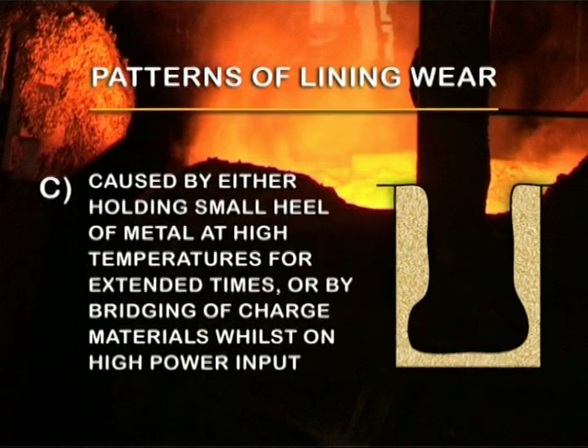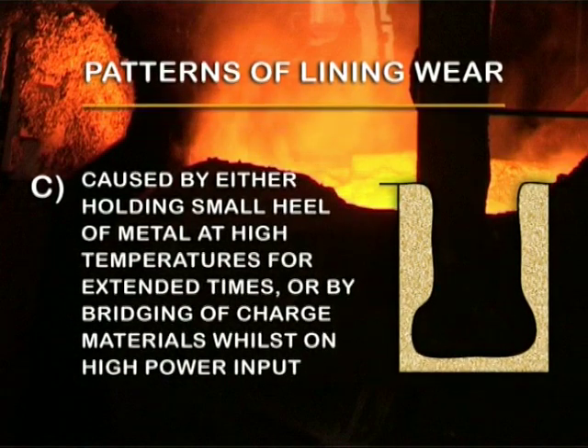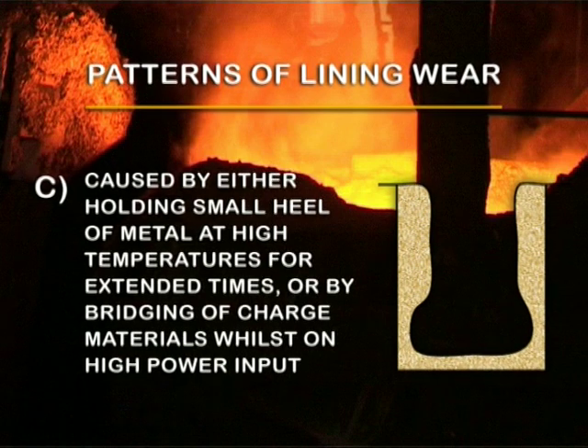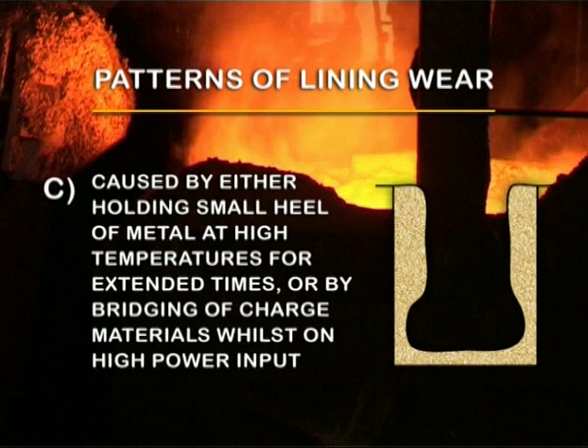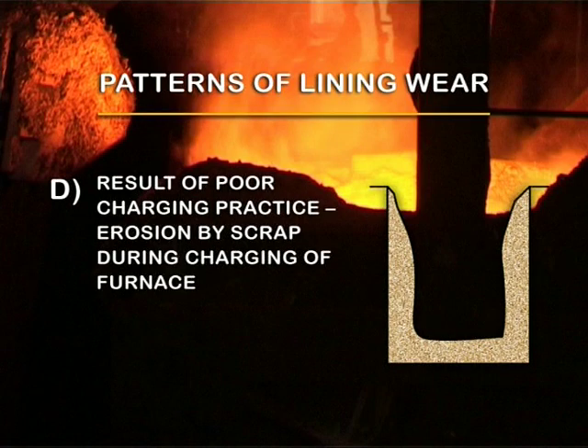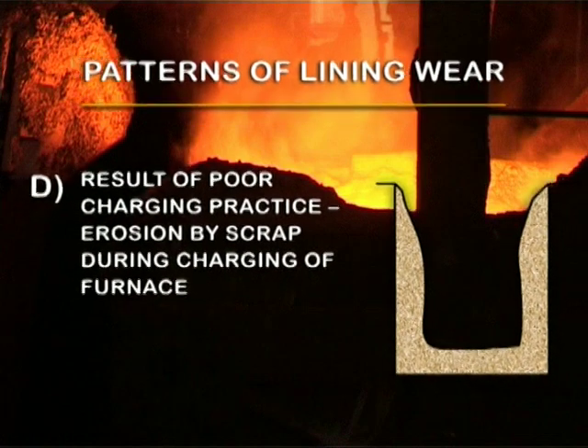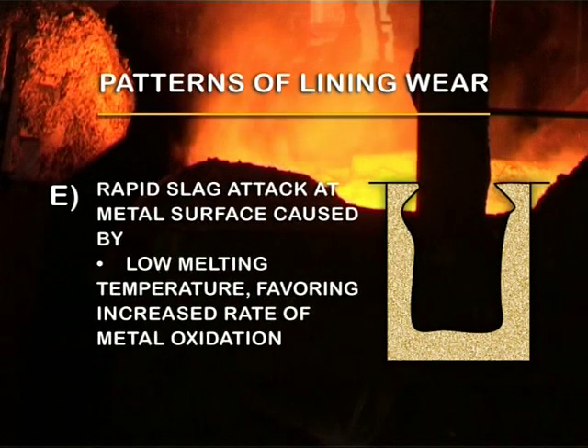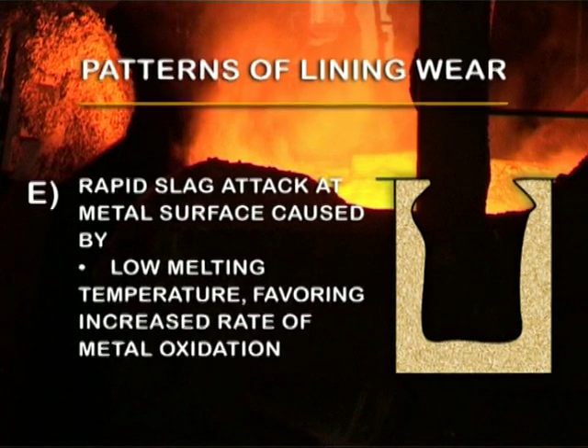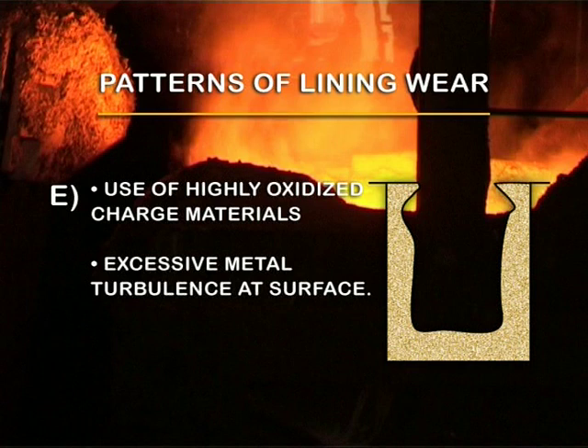Caused by either holding a small heel of metal at high temperatures for extended times or by bridging of charge materials whilst on high power input. Result of poor charging practice. Erosion by scrap during charging of furnace. Rapid slag attack at metal surface caused by low melting temperature, favoring increased rate of metal oxidation. Use of highly oxidized charge materials. Excessive metal turbulence at surface.